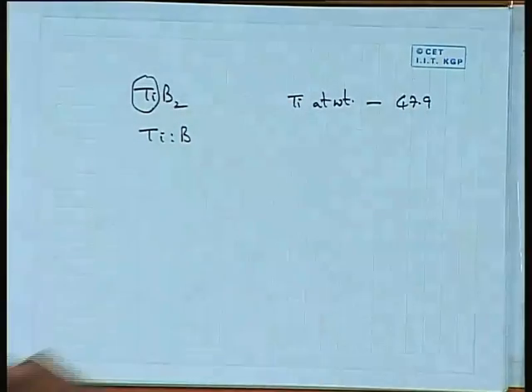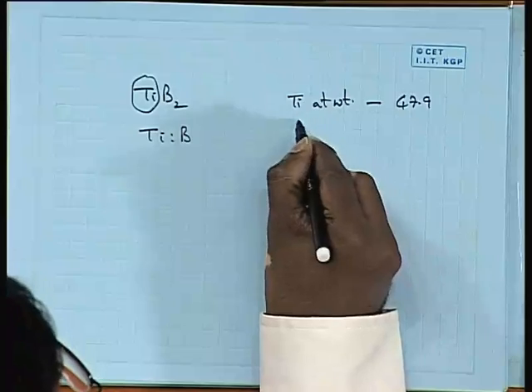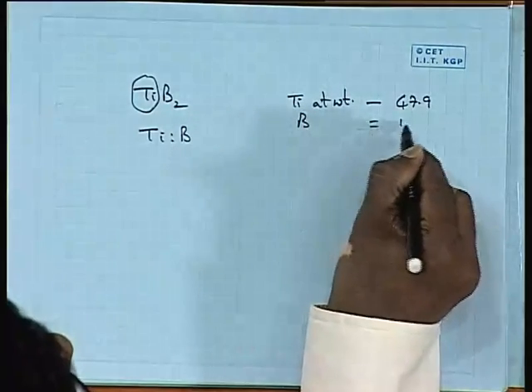Weight ratio, obviously. When I say titanium to boron weight ratio, from the stoichiometry one can find out. Okay, what is the atomic weight of titanium? Anybody remembers? Atomic weight of titanium is 47.9, it's close to 48, and boron atomic weight is 10.8.